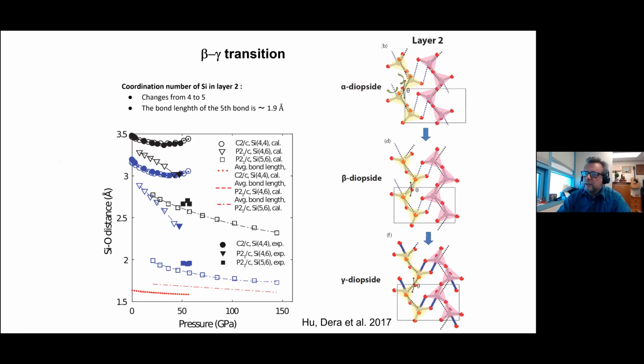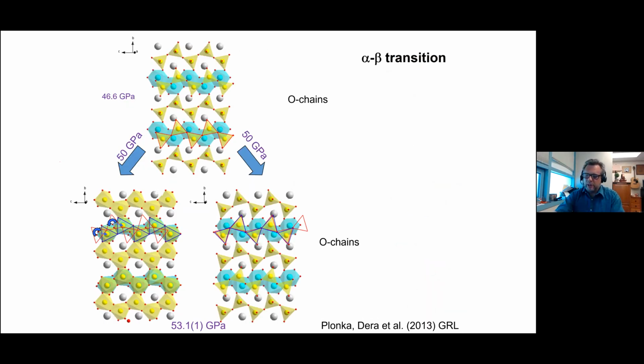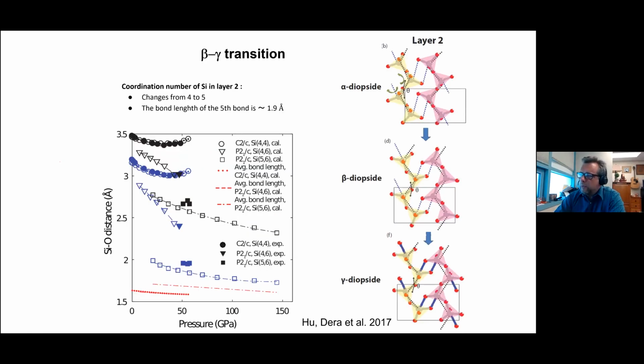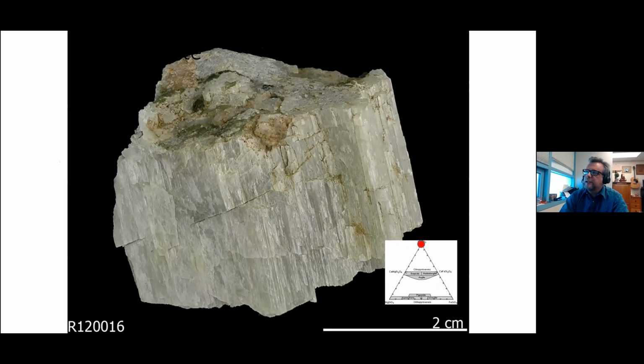One of my CDAC students did some more experiments and some computational project in collaboration with Boris Kiefer, and actually observed that there is a sequence of 2 phase changes. The first one was not seen in this first experiment because we increased pressure too fast. But when we looked more carefully, we saw that there was an intermediate 5 coordinated phase that is stable for about 5 gigapascal range of pressures on compression once you pass this region of phase overlap or coexistence of 2 phases.